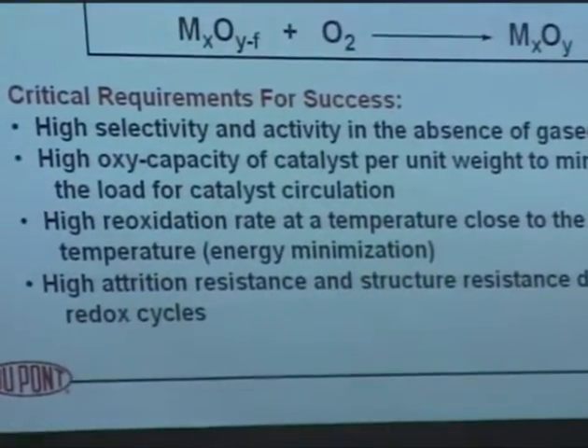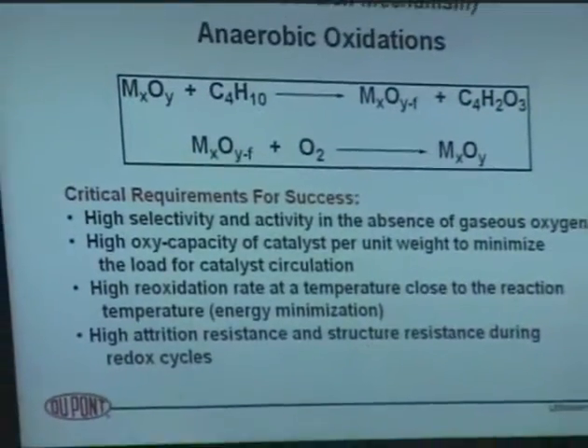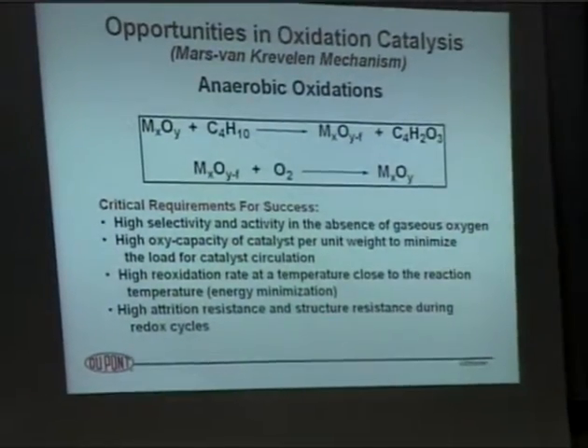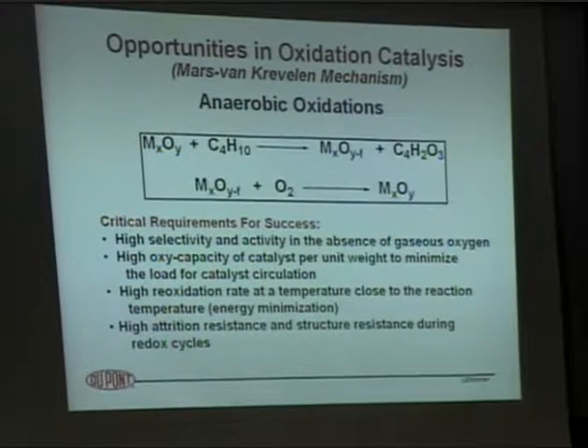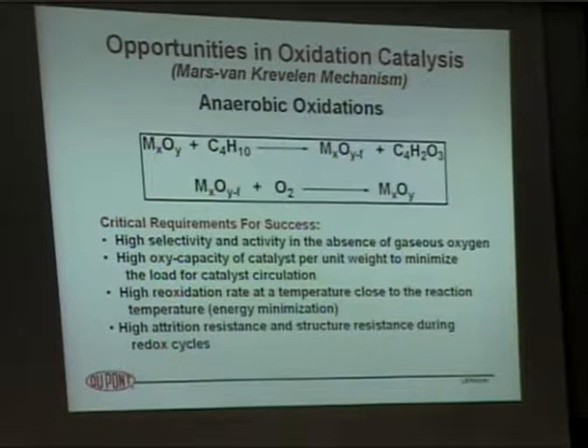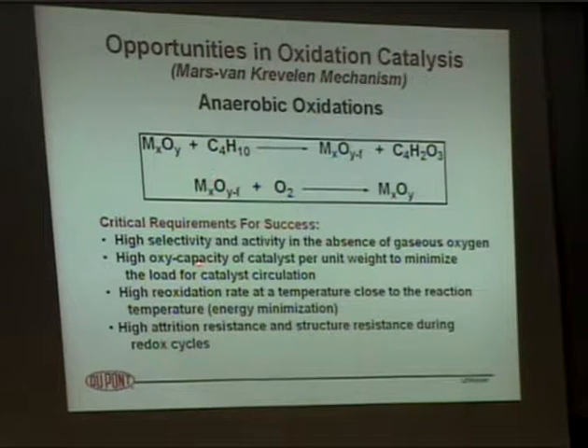Because this is a stoichiometric reagent, all of the oxygen is coming from the lattice. So you've got to be able to pull a fair amount of oxygen out of that lattice on a single pass. Otherwise, it's going to cost you an awful lot of money to circulate the stoichiometric reagent around and around. So you've got to have a lot of oxygen available to oxidize the hydrocarbon. You also need to run this regeneration step at about the same temperature as the reaction takes place. Otherwise, you're heating or cooling millions of pounds of solid on every cycle, which you can't afford to do either. So there are a lot of issues that need to be addressed.